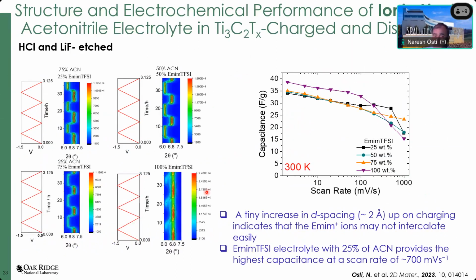Getting motivated from this particular example, we decided to look at the electrochemical performance of the MXene using ionic liquid and acetonitrile, some sort of organic solvent. For this one, we particularly chose acetonitrile and looked into the electrochemical performance and the structural and the dynamic analysis. There is the XRD profile, the in situ XRD profile that we got with the MXene electrode using 100% ionic liquid and with different concentrations of the organic solvent. That means 25 to 75% acetonitrile.